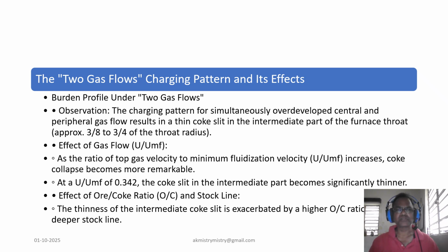The problem was also increased by a higher ore by coke ratio and a deeper stock line. So, these other parameters thin the layer thickness remarkably.